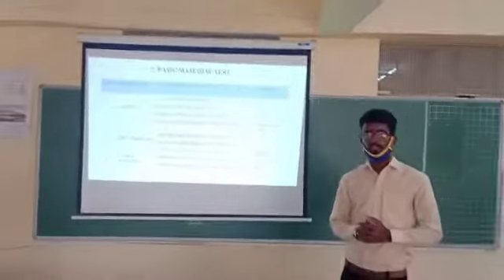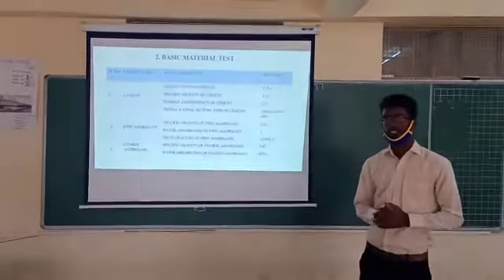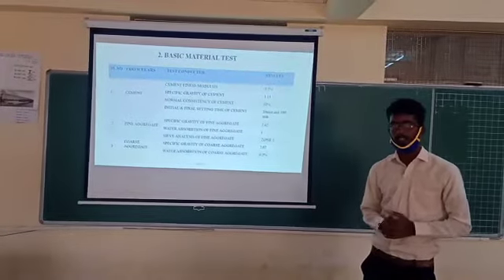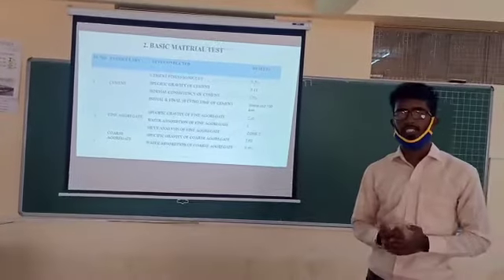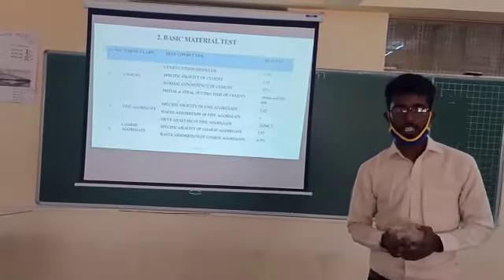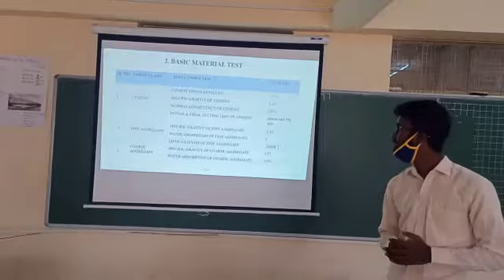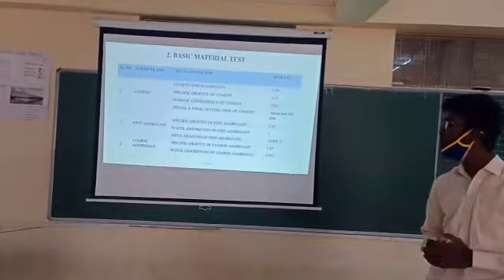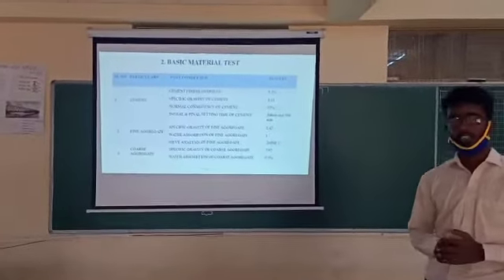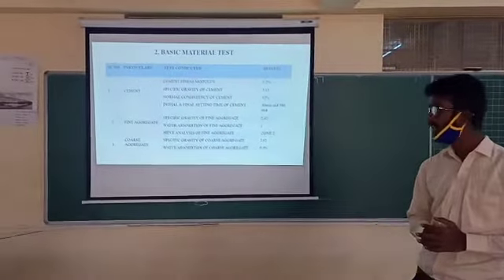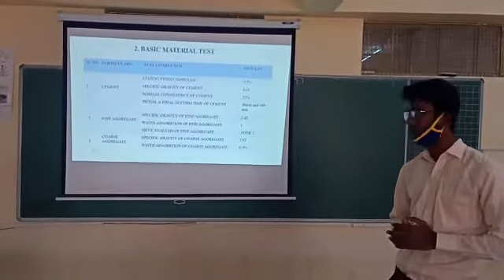And my batchmate will continue for you. We will continue with basic material tests. Some of the basic material tests for cement: the fineness of cement is 5.2%. The specific gravity of cement is 3.15. Normal consistency of cement is 32%. And initial and final setting time of cement is 30 minutes and 580 minutes. For fine aggregate, specific gravity is 2.42. Water absorption of fine aggregate is 1. Sieve analysis of fine aggregate is 2. For coarse aggregate, specific gravity is 2.92. Water absorption of coarse aggregate is 0.5.